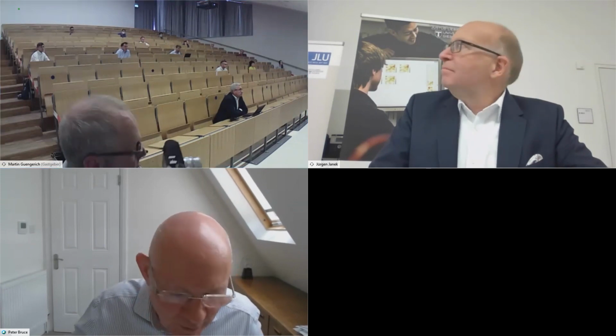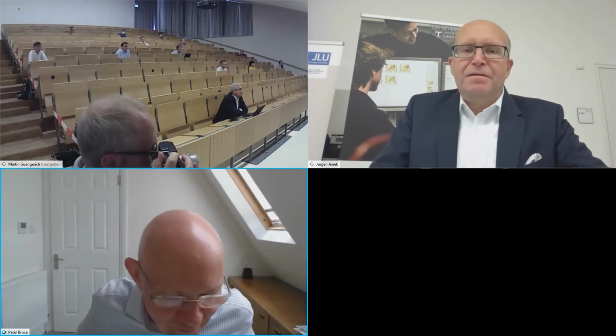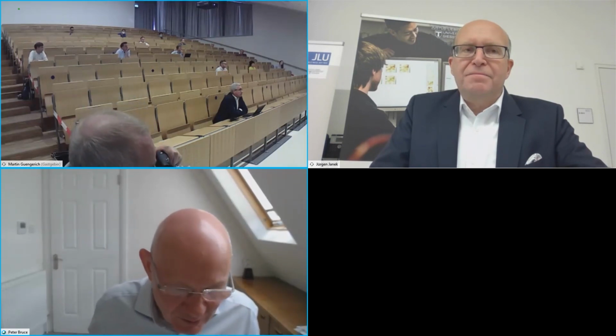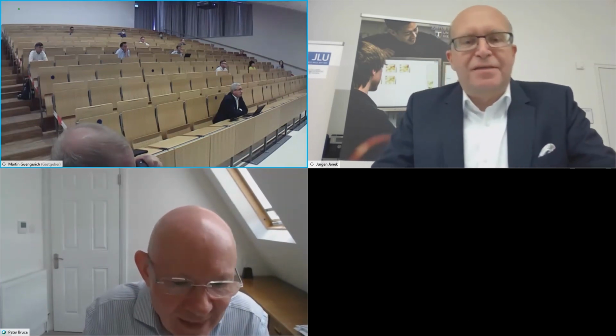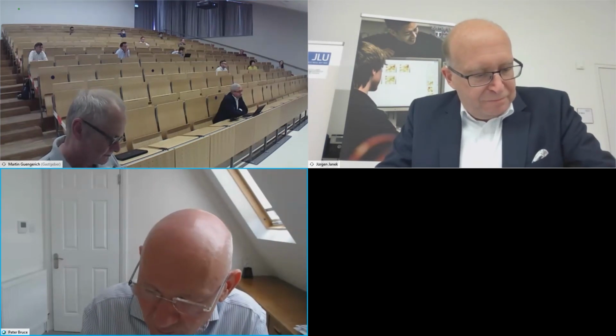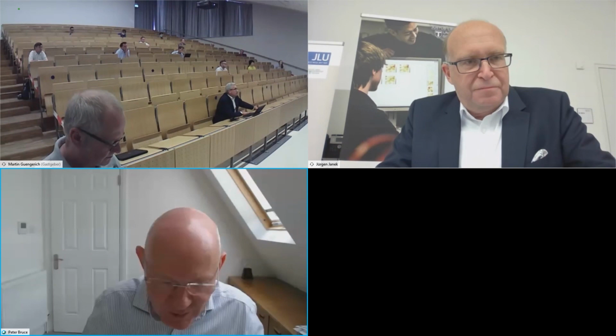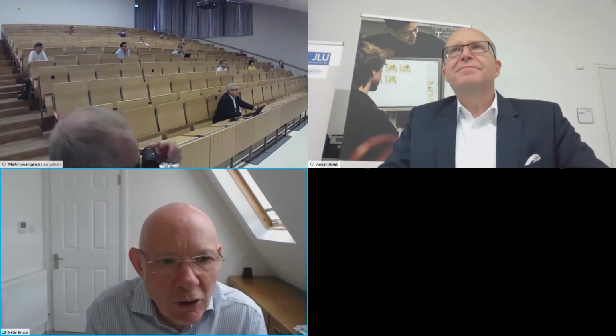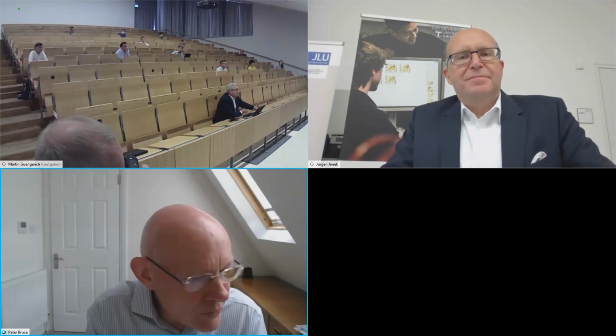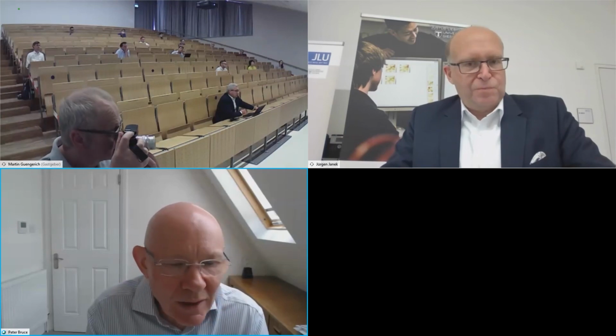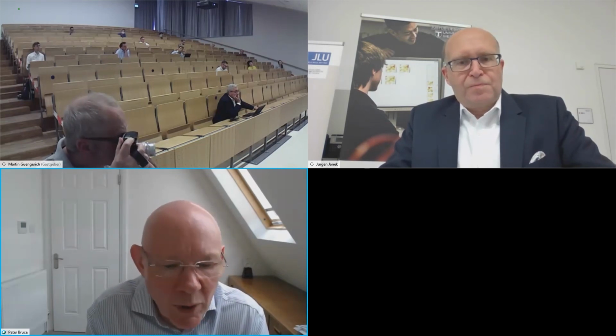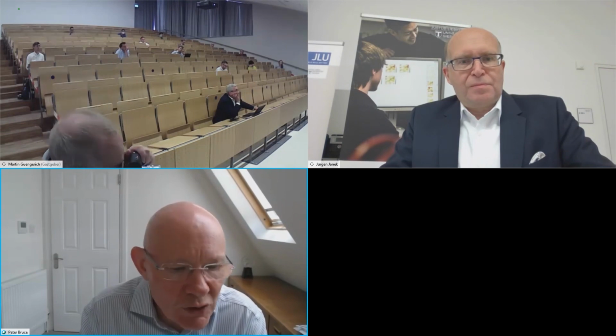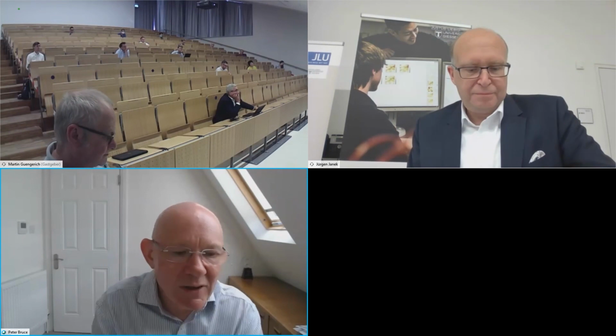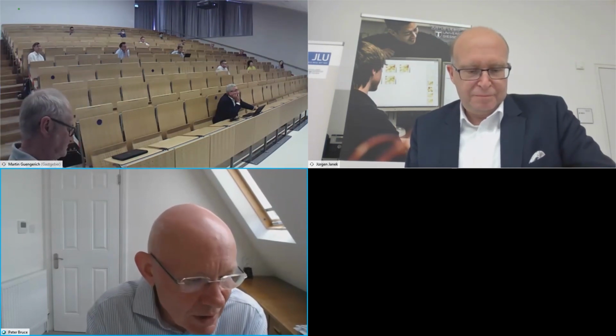Yes, I'm having a little bit of difficulty hearing you in the hall, but I think it's a question of length scales. The first thing to say, of course, is that I didn't get onto this bit of the talk, as you saw at the last few slides, but the balance of how much oxygen is lost from the material, that is, oxygen lost from the surface, versus how much oxygen is trapped in the bulk, is a function to some part of the particle size. So if you go to the real nanoscale, of course you increase the amount of oxygen loss compared with the amount of oxygen redox. That's perhaps at the very simplest level a very significant influence of length scales on what happens.